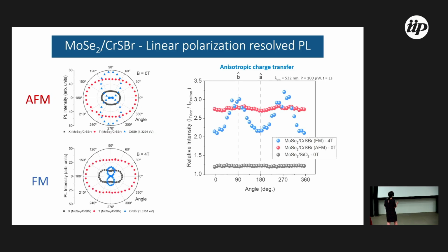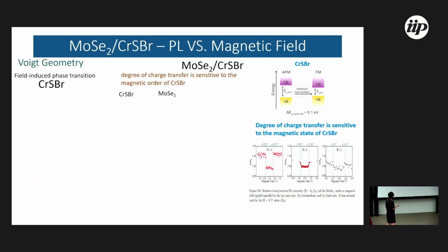What we plotted is the relative intensity of trion and exciton as a function of this angle. I don't know if you know, but the trion increases with doping, so if the relative intensity is changed, it means that the charge transfer is changed, so the charge transfer is anisotropic. Although it's on Z, it's an anisotropic charge transfer. This is clear, and we can also see it better when you apply a field. So this can explain why this MoSe2 seems anisotropic.